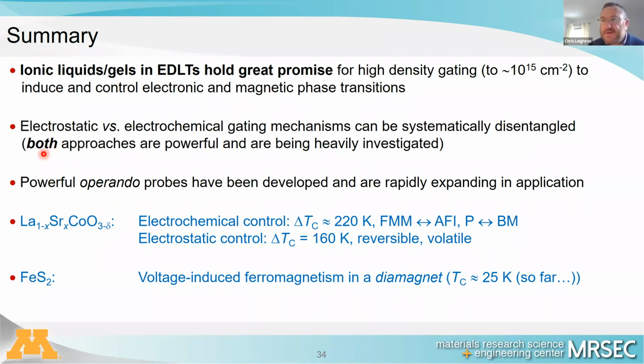Certainly electrostatics and electrochemistry both go on. We believe that they're both very powerful. We have good techniques now to try and tease them apart, so we can certainly understand this. And what I showed you here today in the cobaltites is using an electrochemical mechanism. We can basically toggle between a ferromagnetic metal and an antiferromagnetic insulator.